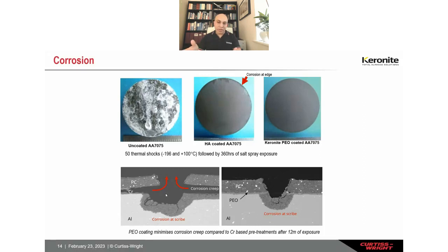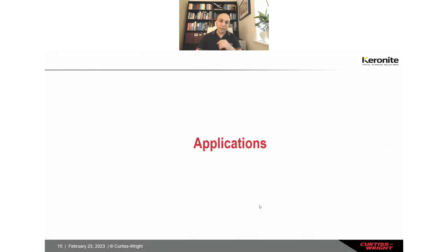The corrosion is migrating underneath the paint, resulting in a blistering effect, and it is deep under the paint. On the right-hand side, as you would expect, because the coating was damaged down to the bare substrate, you will see corrosion happening here, but it is not migrating further because it stopped right there, thanks to a very well adhered ceramic layer. And of course, bear in mind that alumina is electrochemically neutral, so it doesn't accelerate galvanic corrosion. Having an excellent bond with the substrate and with the top coat or subsequent layers gives you very good corrosion protection even when it's damaged.